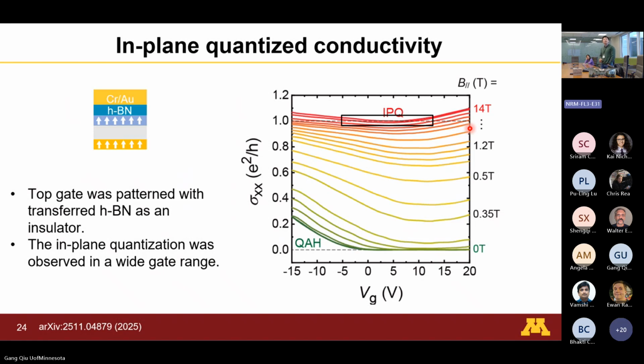Now what we did next is we put on a gate. We wanted to make sure this is not some coincidence, where the resistance value happens to be there. So we put a top gate on this device so you can modulate the Fermi level up and down, and then you do that under different in-plane magnetic fields. The bottom curve is at 0 magnetic field, both layers out of plane. You have these quantum anomalous states, and you have this 0 Rxx. That's the quantum anomalous state, what we expected.